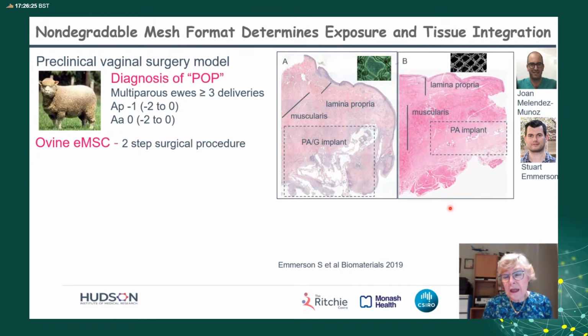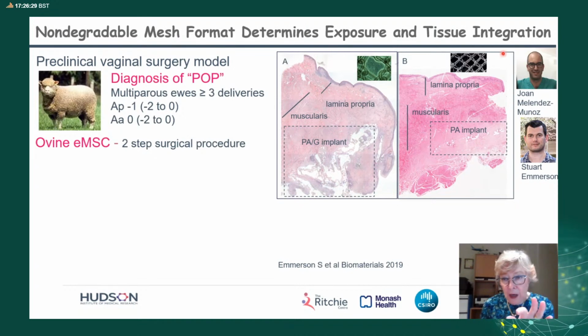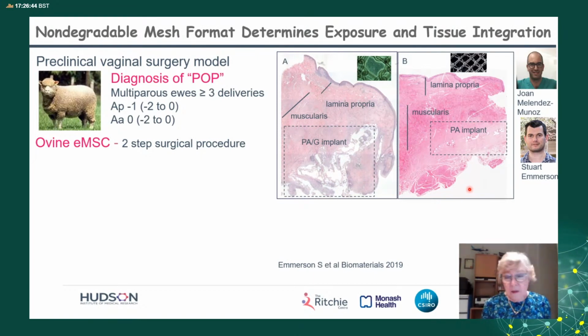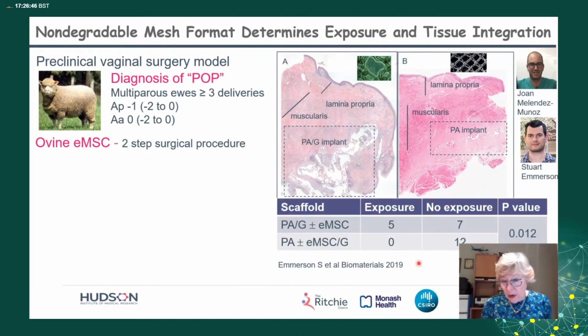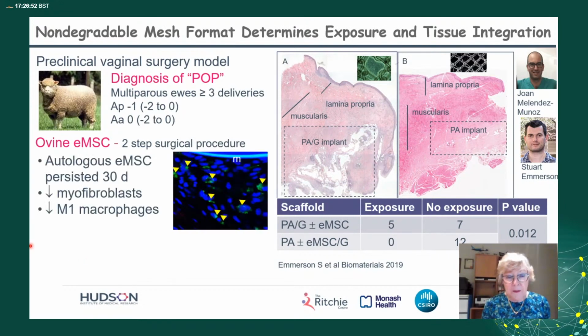And what we did was after we incised, we then laid the polyamide mesh just on its own over the tissue. It lays beautifully because it's so drapable. We then put the cells on in a collagen gel, dripped it on, and then cross-linked it with blue light, and then stitched up the sheep. We found no exposures in our second procedure. It's also much easier for surgeons.